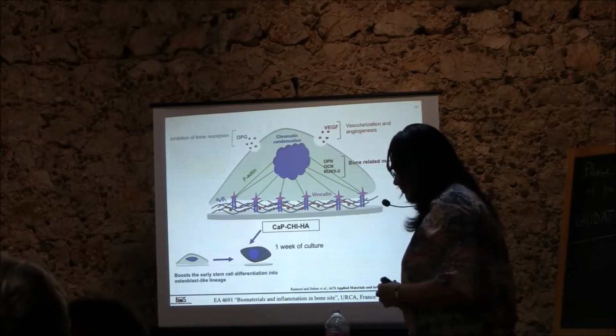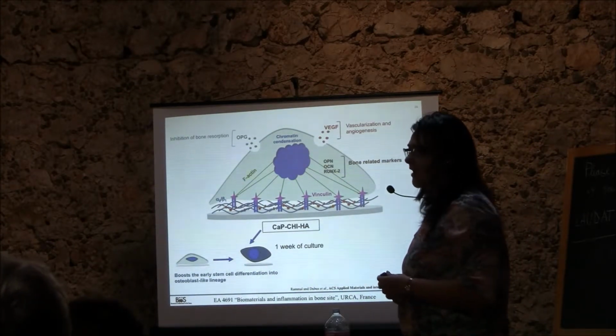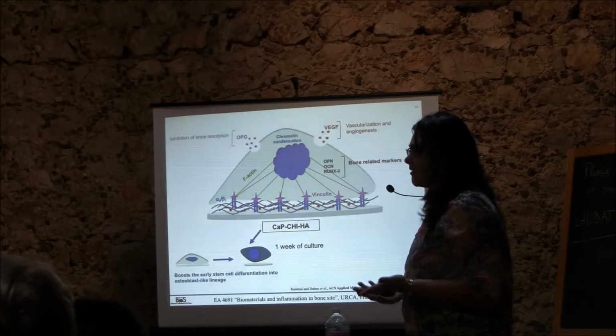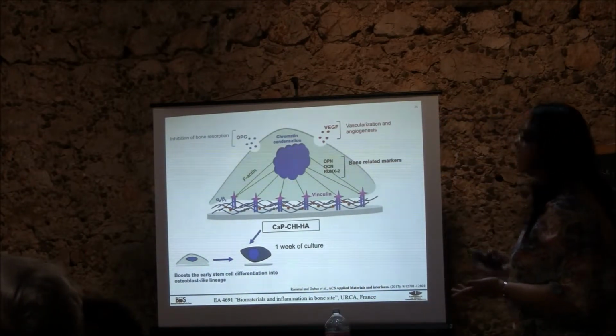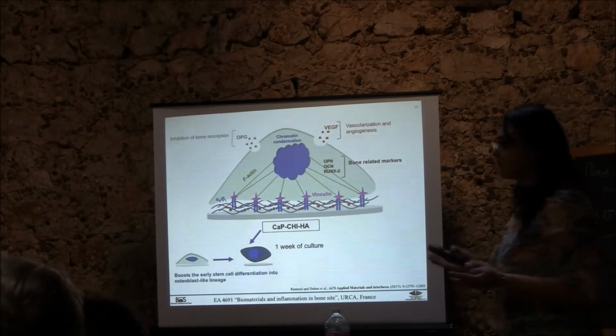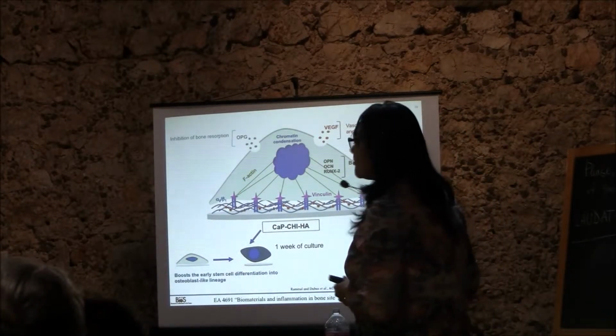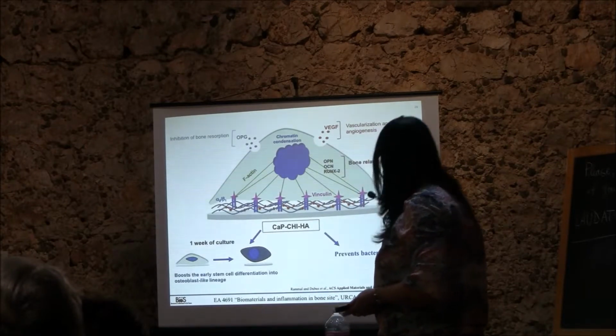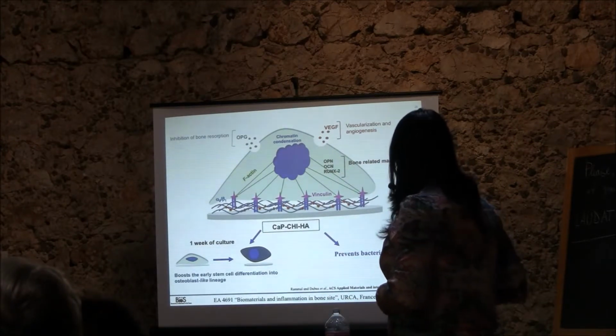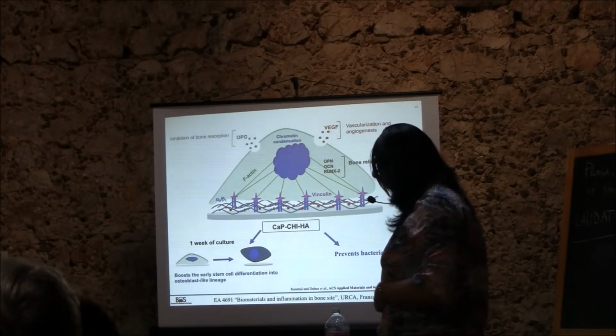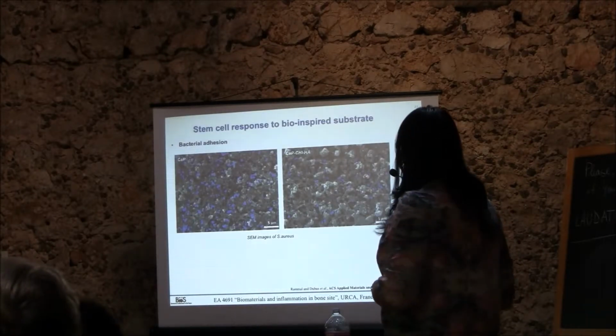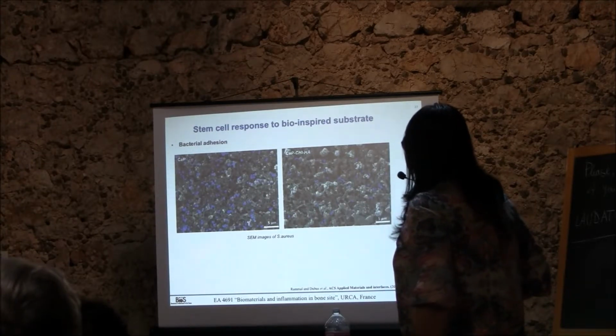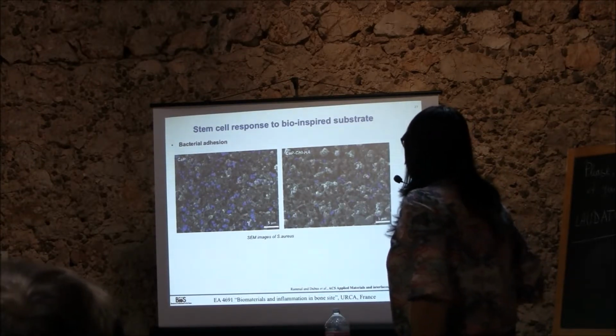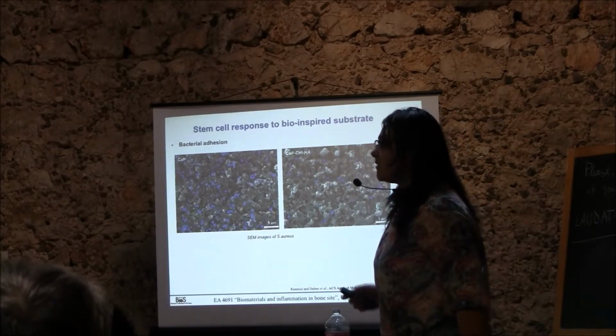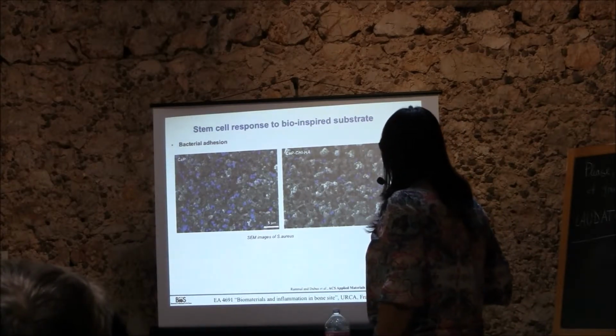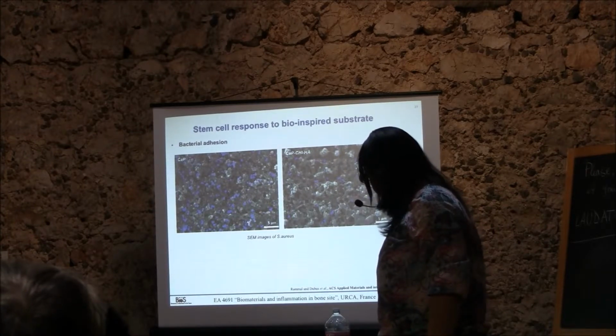But in our laboratory, orthopedic surgeons asked about bacterial adhesion. What about bacterial adhesion? Because 10% of failures of prostheses are attributed to infection. So we checked if our coating prevents bacterial adhesion, and we observed a significant decrease of bacterial adhesion when we added molecules such as chitosan and hyaluronic acid.